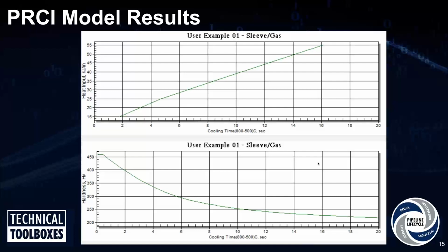So if you have a specific hardness, say 300 or 400 Vickers, you can use the bottom curve to predict, for that 400 Vickers, what your cooling rate is, and then use that cooling rate on the top curve to predict what that heat input would be. And that would be the heat input that you need to make that weld to hit that hardness exactly. If you weld at a higher heat input, that weld will cool slower, so your hardness will start reducing.